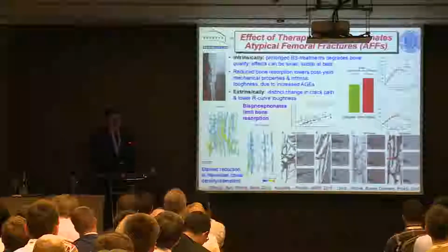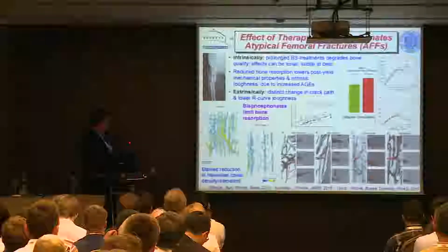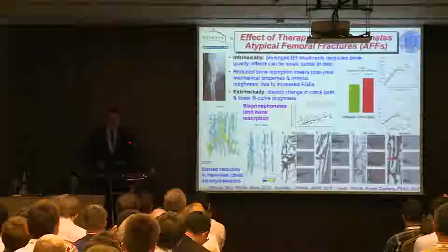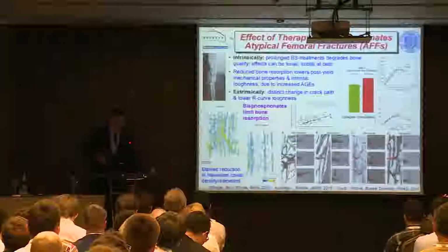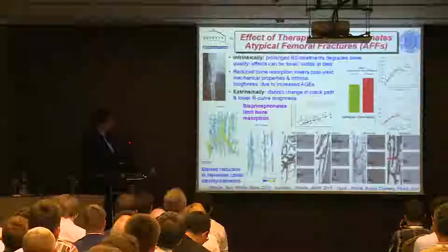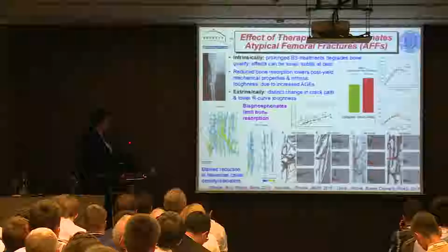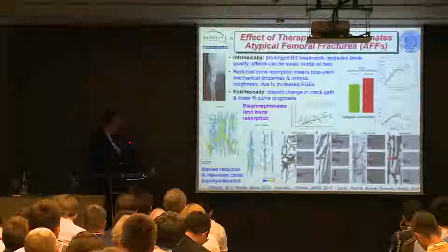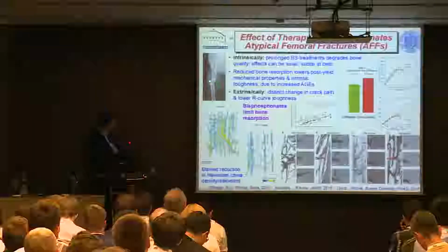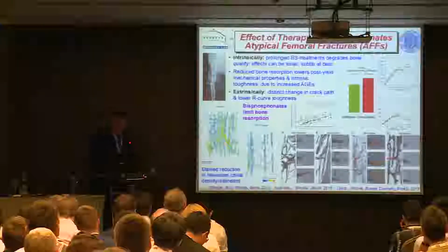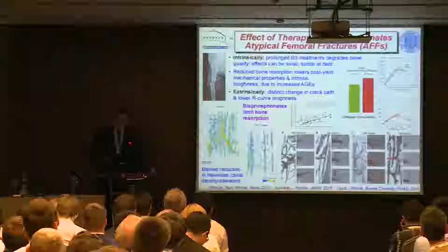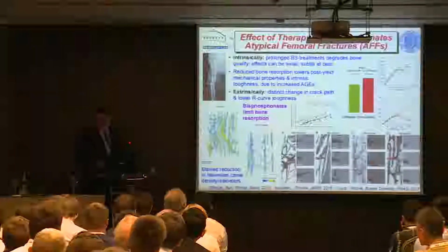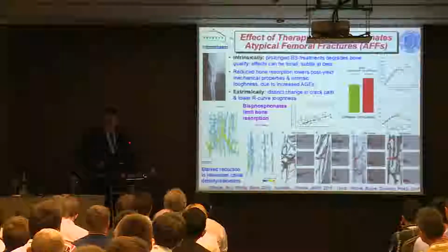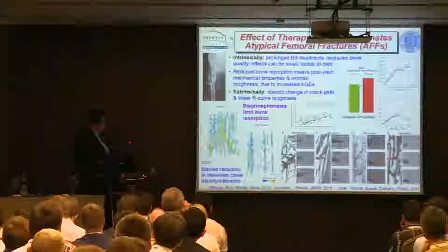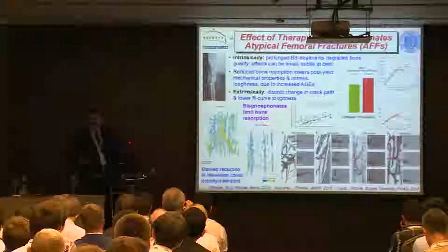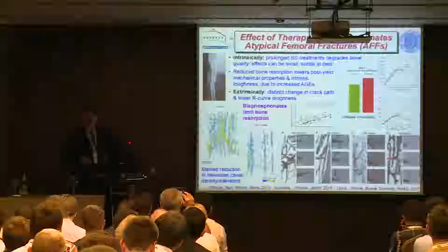This is an example of this from a problem with use of bisphosphonates. These are widely prescribed to deal with osteoporosis, particularly in women, and they work by limiting bone resorption, but a small portion of the population suffers these so-called atypical femoral fractures. They get sudden breaks of their femurs. Relatively young people get this if they've taken these drugs, and it only accounts for about 0.2% of the population who take these drugs, but it's such a critical fracture that the use of bisphosphonates has dropped dramatically in the last 10 years because of fears of this.